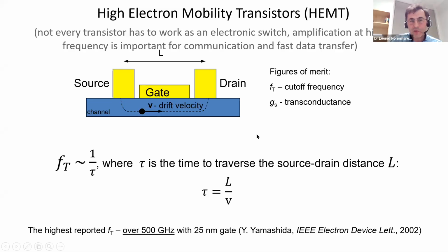And as you can see from the simple image, the time which is needed for an electron to travel under the gate is simply the width of the gate, L, so the distance between source and drain, divided by the drift velocity of electrons. And from this simple relation, you can understand what the strategy should be in order to make a transistor fast. So we have to either make this distance smaller, or we can increase the drift velocity.